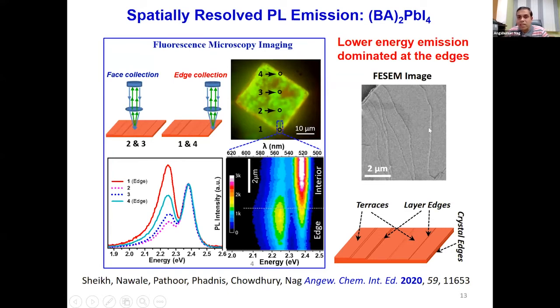So in this layered structure, not only at the crystal edges, but on the surface of the crystal also you see lots of edges. Therefore we termed these layer edges, and layer edges are there in addition to the crystal edges throughout the surface of the crystal. Because of that, throughout the surface of the crystal, we see some tiny contribution from the lower energy emission, which dominates at the crystal edges.